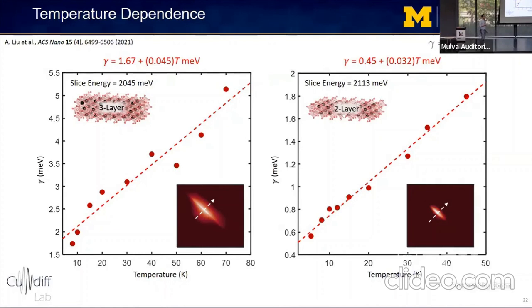And if we extrapolate this homogeneous line width to room temperature and compare it with the inhomogeneous line width, we can reach a concrete answer to the question I posed at the beginning of this part of my talk, which was, are perovskite nanoplatelets homogeneously broadened? And the answer, it turns out, is it depends.